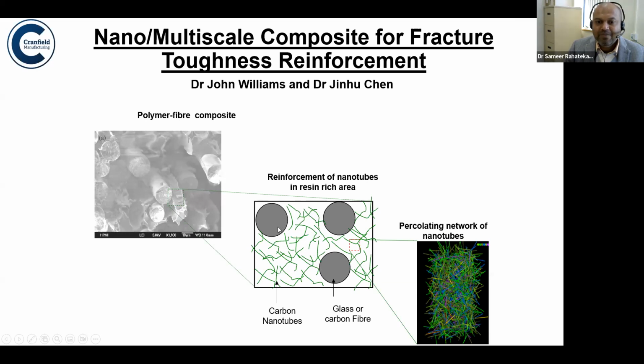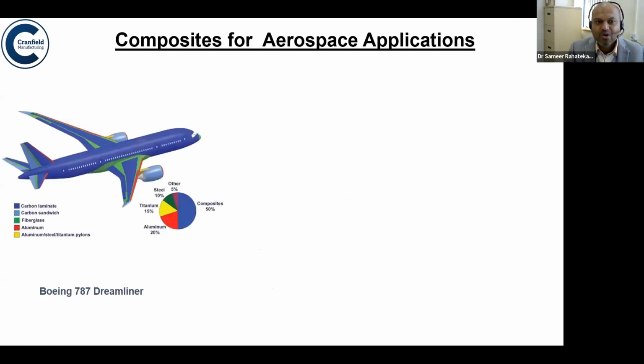You will have gaps between these carbon fibers filled with epoxy and carbon nanotubes, which are much stronger than the baseline epoxy. And therefore you can get better mechanical properties compared to just using epoxy as a glue. Okay. So why is it important? Because more than 50% weight of your aircraft is made from composite materials like carbon fiber.